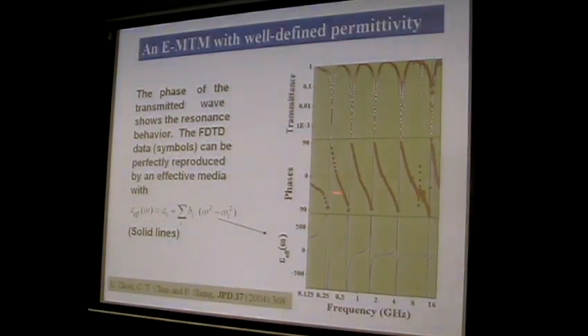And also this effective medium model naturally gives an explanation why the total transmission can happen. In between two resonances where the total reflection happens, we always have a particular frequency where the effective dielectric constant equals 1. That means the system becomes transparent at these particular frequencies. That's why at this frequency the total transmission can happen. Physically, this happens because the two currents for these two resonances are just out of phase and they cancel each other, seen at the far field.